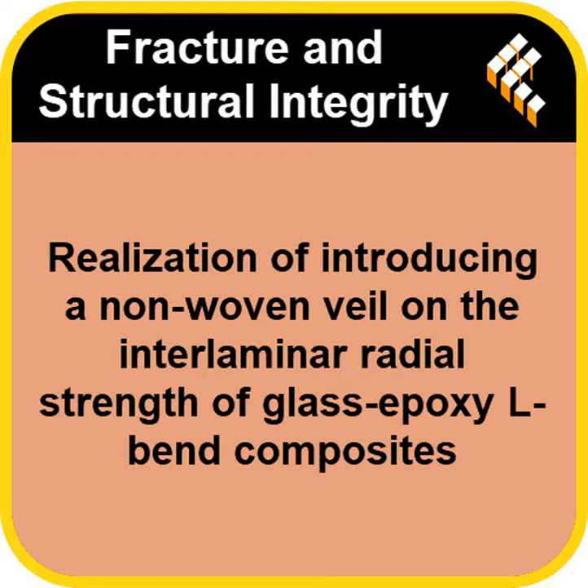They absolutely did. The visual evidence from the SEM was really compelling and lined up perfectly with the mechanical test data. So what did the fracture surface look like on the baseline sample, the one with no veil? It looked, well, weak. The glass fibers from the main composite layers seemed loosely attached to the epoxy matrix around them. You could almost see where they just pulled right out. It screamed weak interface. Just peeled apart easily, like you said. Yeah, classic adhesive failure between layers.